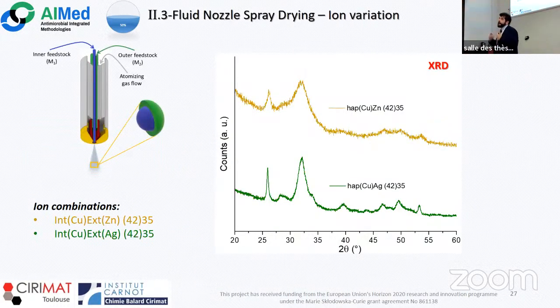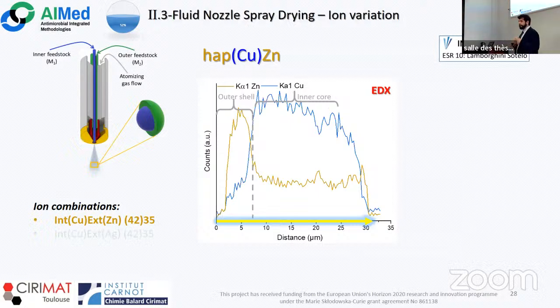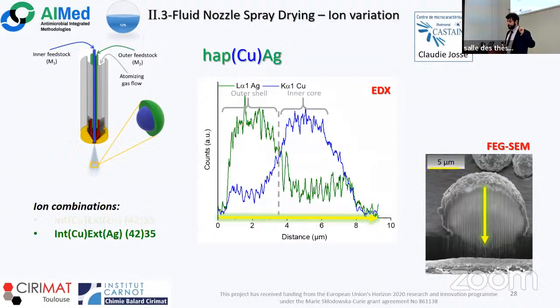Now, we wanted to vary the ion, because maybe zinc and copper could have been just a lucky shot. So we tried two other combinations, both with copper as the core, with zinc as the shell in one case and silver as the shell in the other case. And as we can observe, in both cases we have the zinc in the shell outside and the copper segregated inside, and the silver in the shell outside and the copper segregated and well separated.